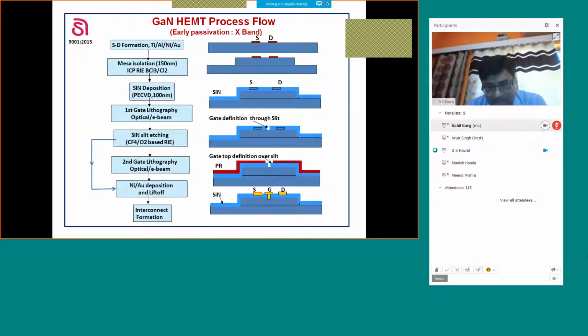And this is the process we normally follow for X band or Ku band devices, where, as I told you, we have to maintain the initial charge state of the GaN HEMT surface. So this technique is basically based on early passivation. Once we fabricate source and drain contacts and do implant isolation or mesa isolation, then we passivate the complete surface of the wafer, and then by using electron beam lithography we open a small gate dimension, and then using dry etching we etch this small slit, which basically decides my gate length. And then in a second electron beam lithography I define the head of my gate.